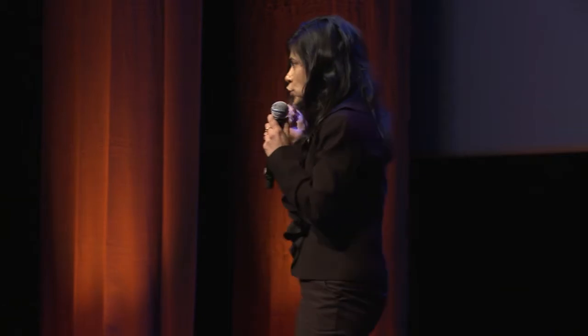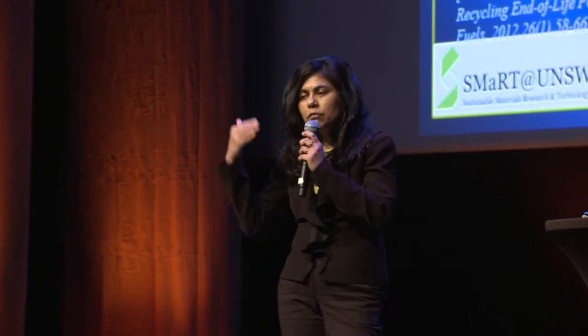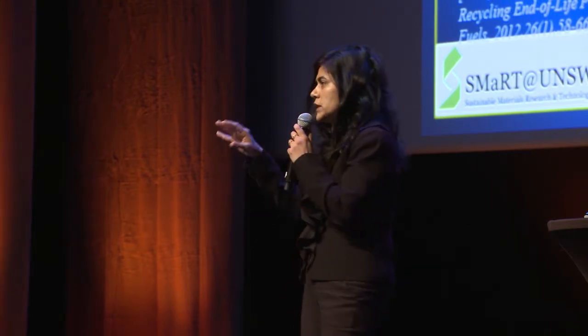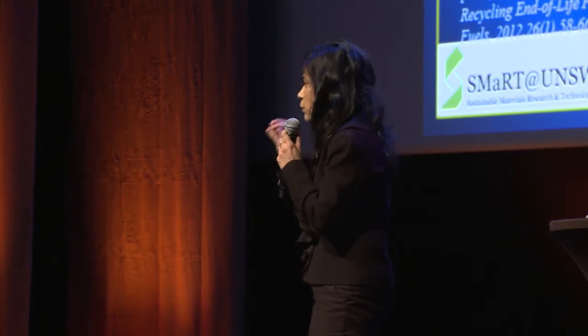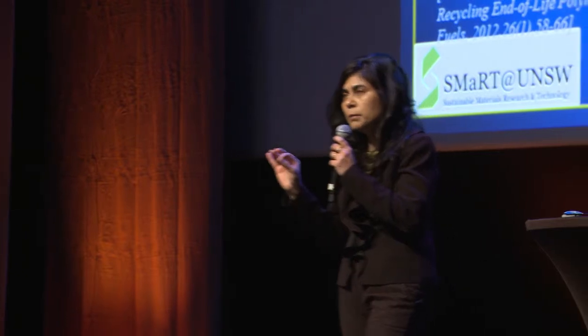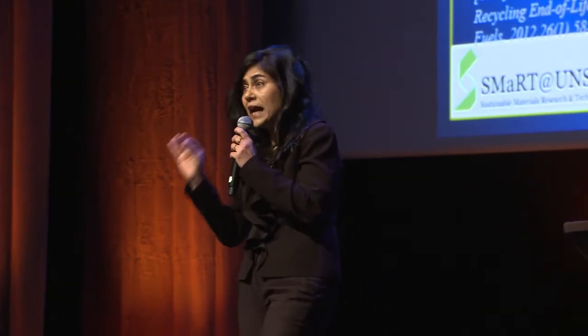But the minute you introduce polymeric materials, we've shown some examples there, you can see the contrast. HDPE, rubber, PET, all of these different types of blended mixes were used as carbon inject materials, so that's for purposes of slag foaming.